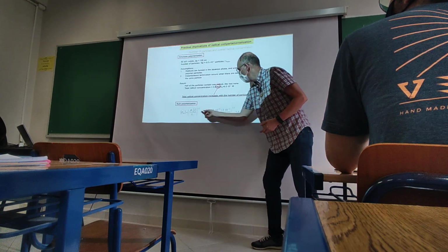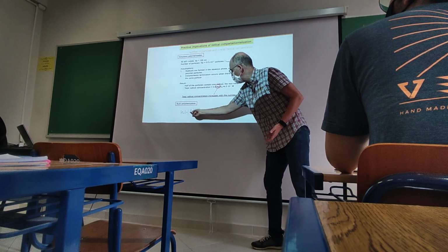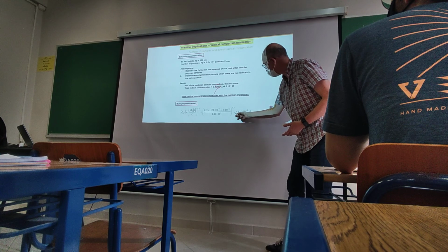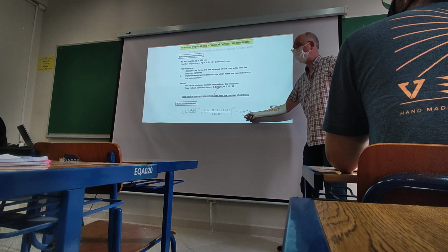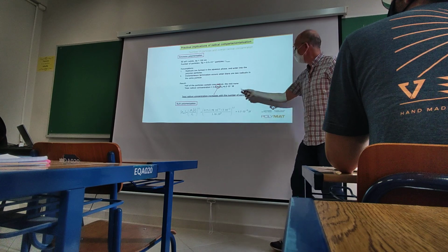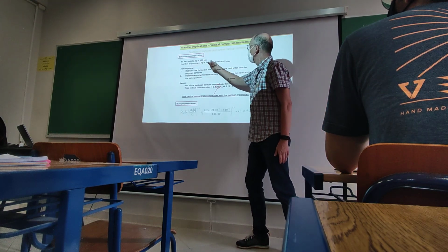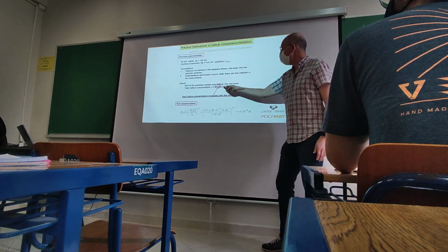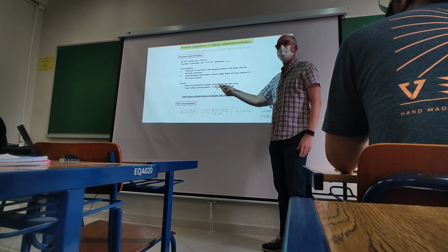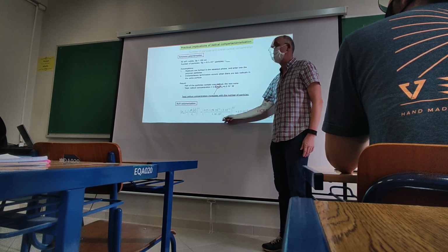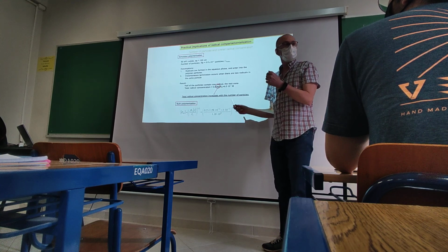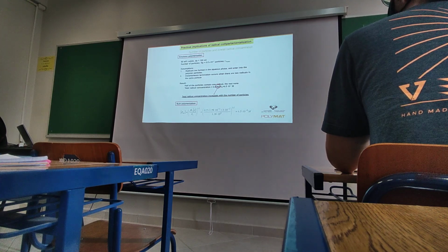For the normal values that we use, for the composition of initiator, like the one I showed you before, and for the same initiator concentration, the radical concentration you obtain is 4.5 to the power of minus 8 mole. In emulsion polymerization, in this case, you have one order of magnitude more concentration. And I can go even higher if I change the number of particles at the same temperature and initiator concentration. So in emulsion polymerization, I can control the polymerization rate and the molar masses by controlling the number of particles that I generate.